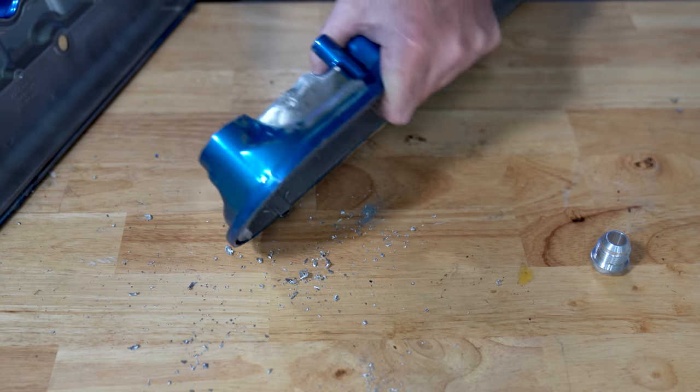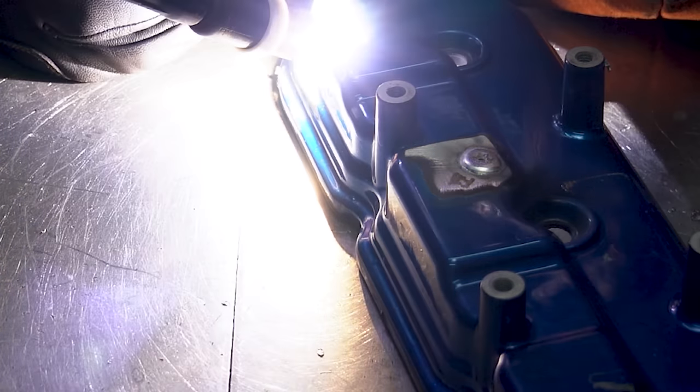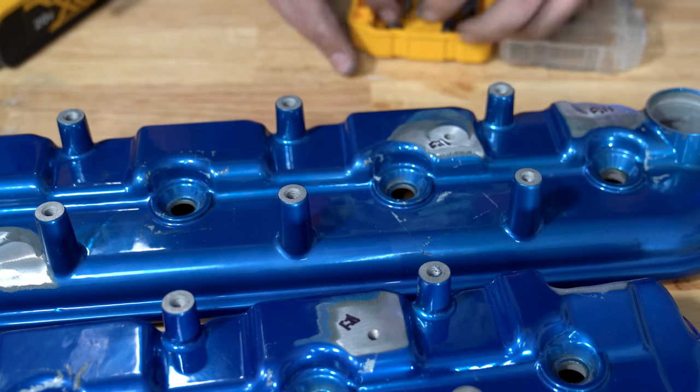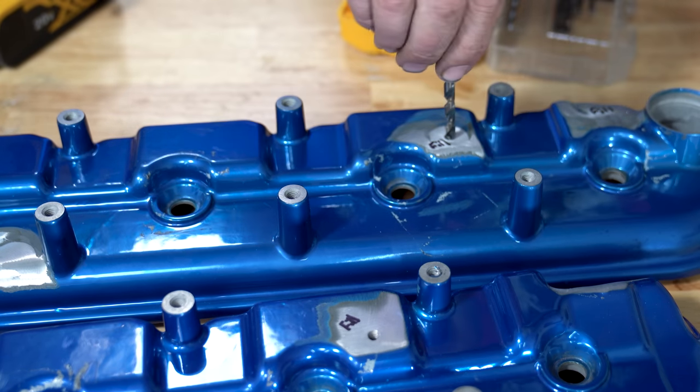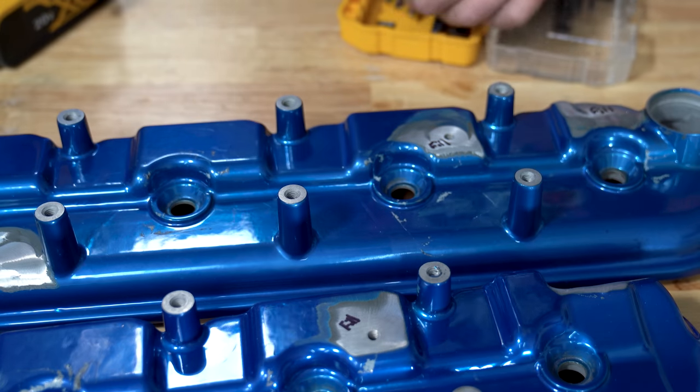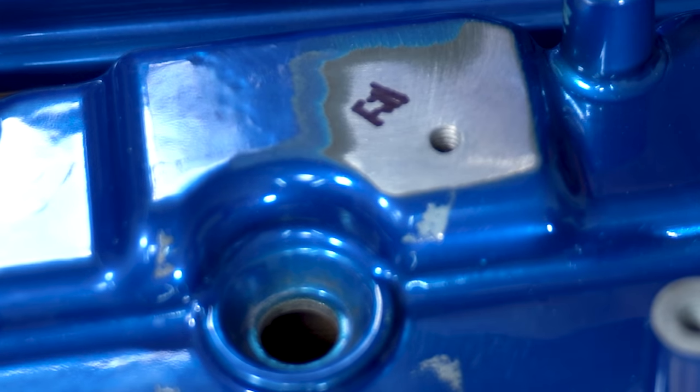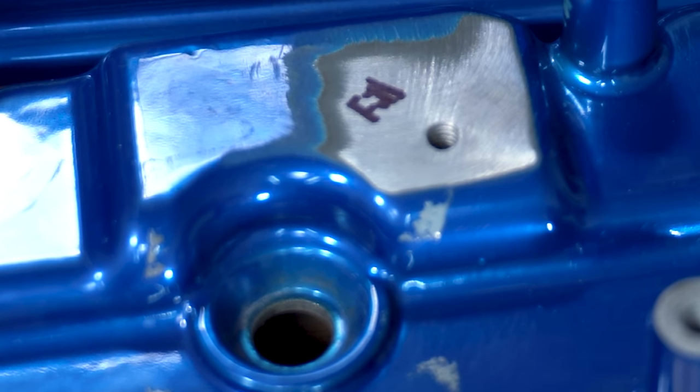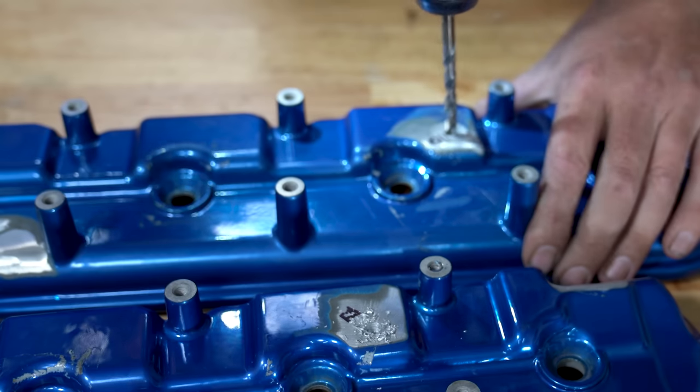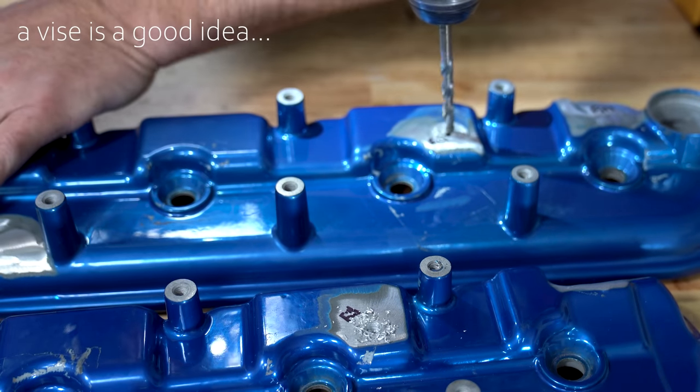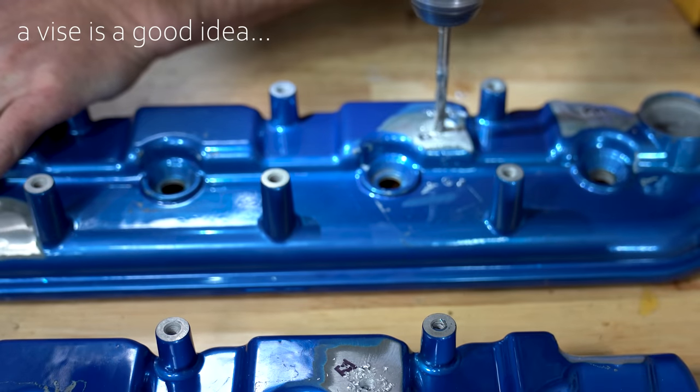Since I have two valve covers to do, I'm going to skip the correct prep on one of them and show you what happens as a result. This is a super simple, easy job. Since these valve covers are a cast material, we need to get a nice fresh layer of metal to work with, since cavities like these bolt holes often keep trapped dirt, oil and grease contained within them. The fastest way I have found to clear all of them out is to drill them out to a diameter that is only slightly larger than its current diameter.